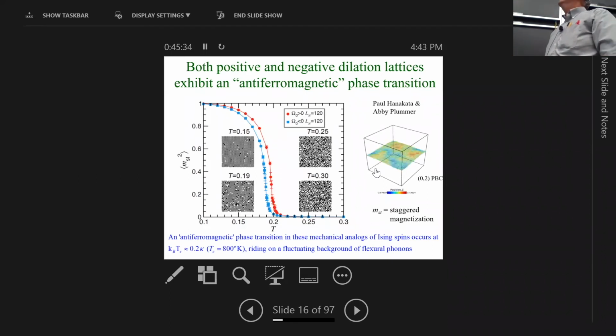Couldn't do it in water, but now this antiferromagnetic order parameter is riding on a fluctuating background of flexural phonons. So it's not a simple compressible Ising model. It's more like a compressible Ising model on steroids, as I'll try to convince you. Okay, so this is roughly where we think the Tc is. We think there's a t to the 1 minus alpha singularity, for those of you who remember the ancient days of critical exponents, where alpha is the specific heat exponent. So, please. Yeah, of course.